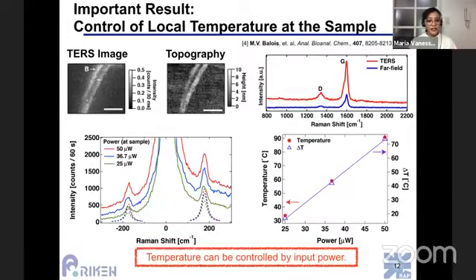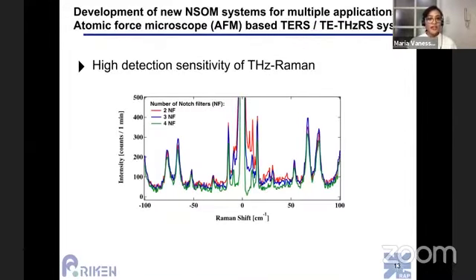And lastly, going back to the temperature, we found that you can control low temperatures, less than 100 degrees Celsius, by simply controlling the input power. And with this, we found that this is very much an exciting topic to pursue. And right now, we are trying to improve the detection sensitivity of low frequency Raman by also increasing the number of notch filters in our system so that we can have a better signal to noise ratio. So here you can clearly see from the 2-notch filters to the 4-notch filters, particularly at the center, which is close to the Rayleigh line at 0 wave number, the peaks, especially in the anti-Stokes, can be clearly seen for the 4-notch filters that were used.